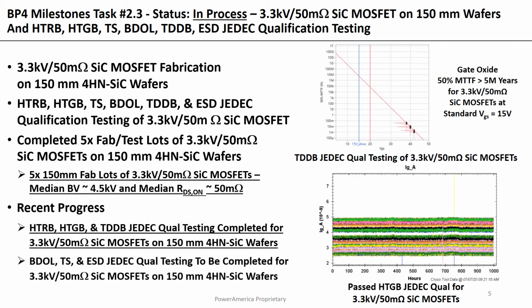We're also working on body diode operating lifetime, thermal shock, and electrostatic discharge JEDEC qualification testing for these 3.3 kV 50 milliohm silicon carbide MOSFETs. Again, this is all done on the 150 millimeter wafer fabrication.